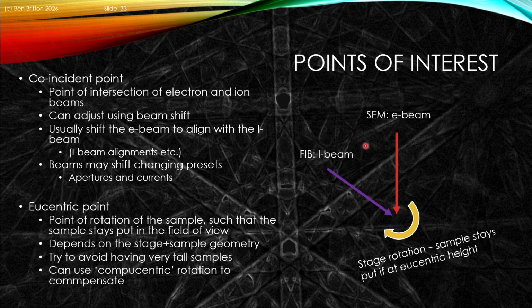So we have just a few key geometric points. We have where the beam, the FIB and the SEM are located, and they point at the sample. This particular point is the so-called coincident point. And that will be aligned specific to your microscope configuration. There may be very slight offsets. Ours, for instance, is set to be about 6 millimeters if the beams are well aligned, and we just do a little touch-up to make sure that happens and we understand where that coincidence sits.